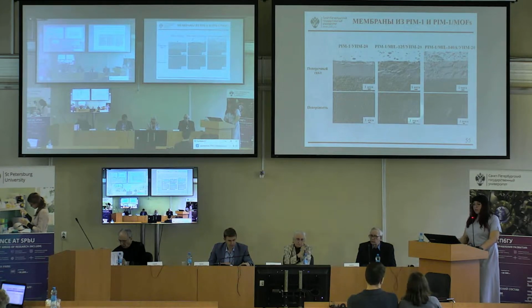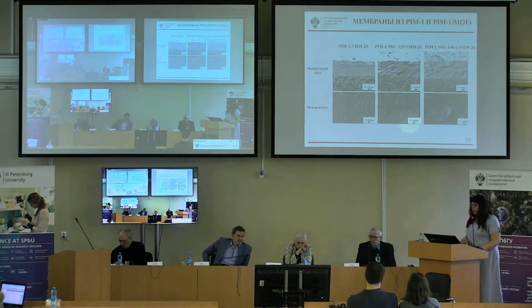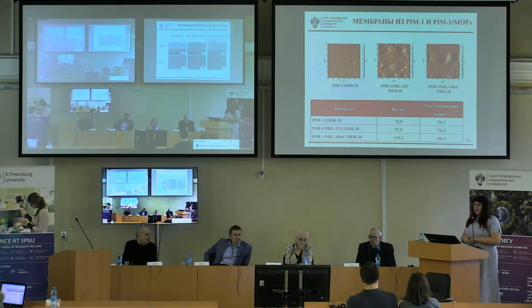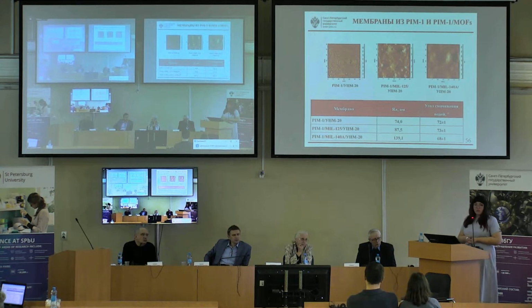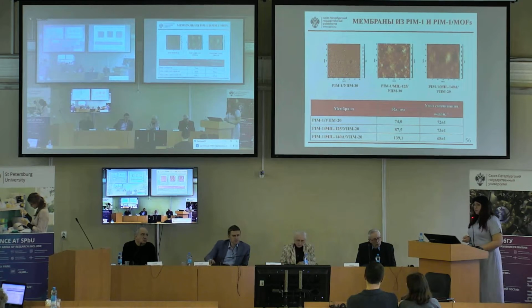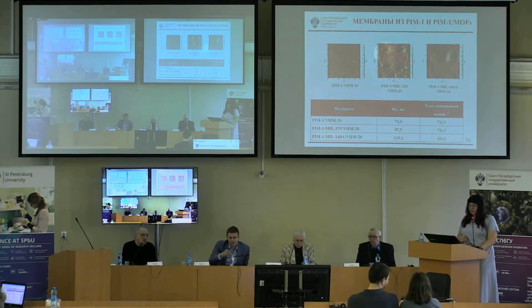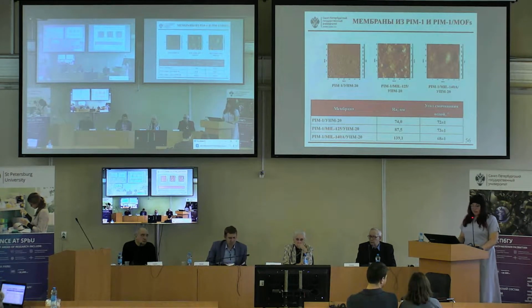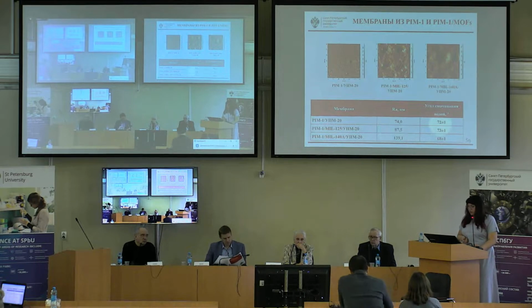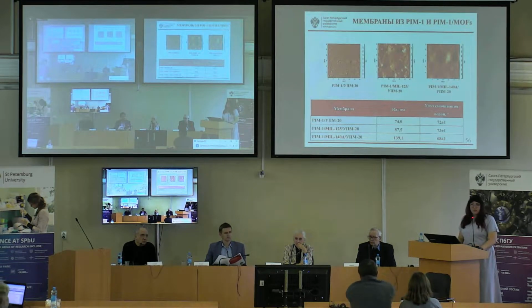It was noted that incorporating MIL-125 and MIL-140A into the PIM-1 matrix results in a rougher cross-cleavage structure. Non-through pores are observed on the surface of all nanofiltration membranes, with size and number depending on the modifier. Compared with the unmodified membrane, introducing MIL-125 leads to a significant decrease in the number of pores and an increase in their size, while introducing MIL-140A decreases the number of pores without significantly changing their size.